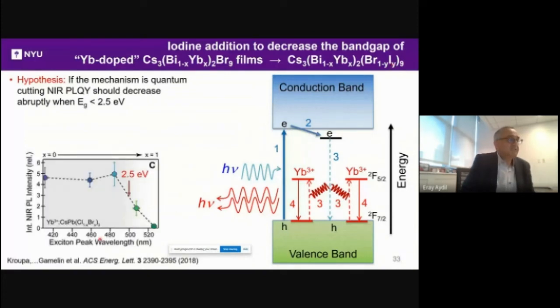So this was done in the case of cesium lead chloride and bromide. In that case, the cesium lead chloride bromide bandgap is greater, so instead of substituting for iodine, they decrease the bandgap by substituting chlorine with bromine. As you go down the periodic table, you can shift the bandgap, so they didn't have to resort to iodine. They could just add bromine into the chloride and decrease it. And look what happened. Just around 2.5, the photoluminescence quantum yield took a dive and went to 0 from something like 200%. This is a normalized relative intensity, but it's going from something like 200% to nearly 0. So we want to do this with that material.